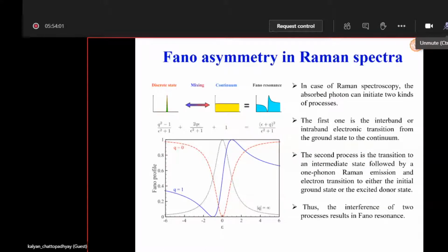You know that whenever you are studying Raman, it is possible to have an interference between the intraband transition and the optical phonons. So these two transitions can interfere, and that will lead to, for example, the asymmetry in the Raman peak. If you have some idea of how this asymmetry is coming, and you can theoretically formulate what is governing this Fano asymmetry, then it is very interesting to get some idea about the hole dispersion and the valence band dispersion. So this is basically a discrete and continuum interference, and that gives rise to this asymmetry in the Fano resonance.